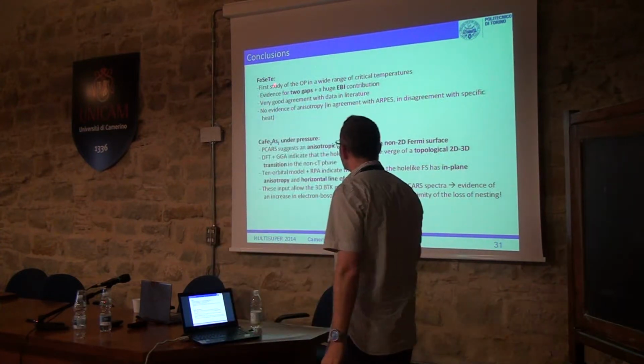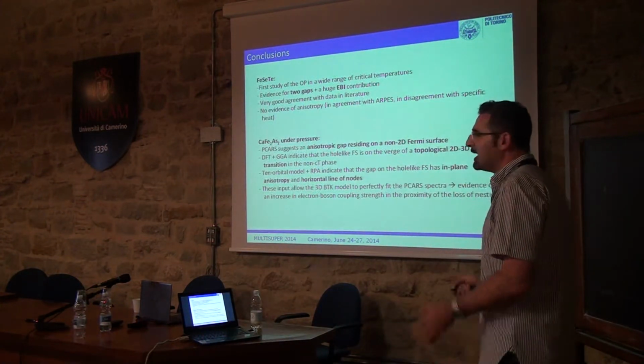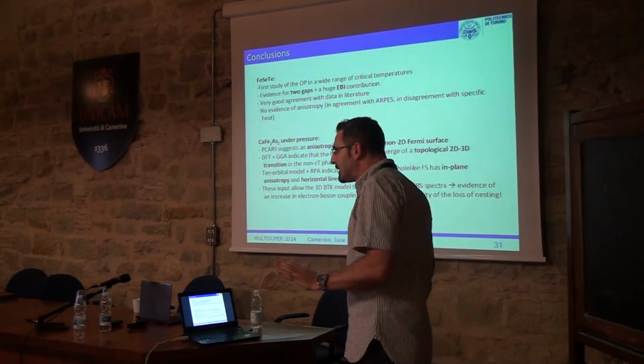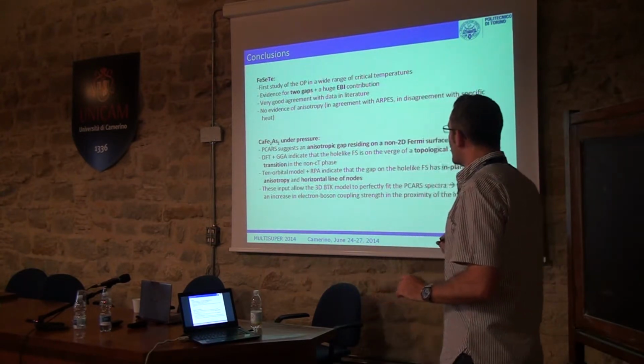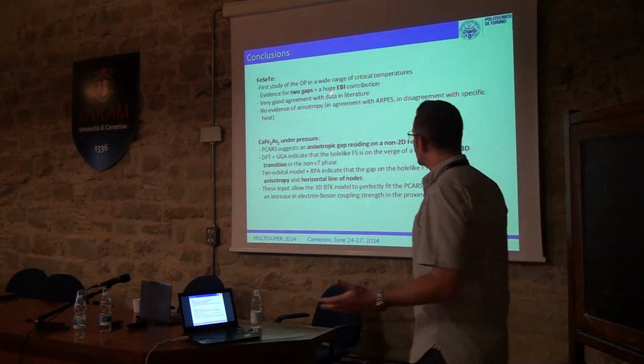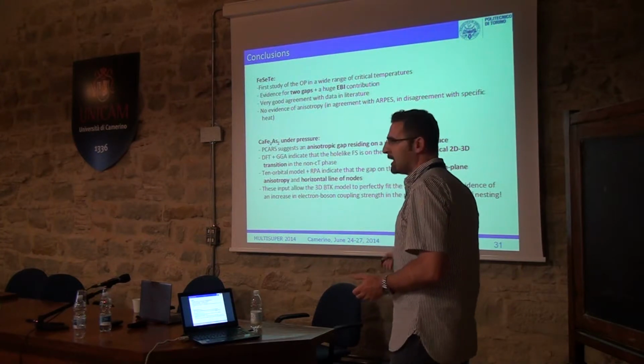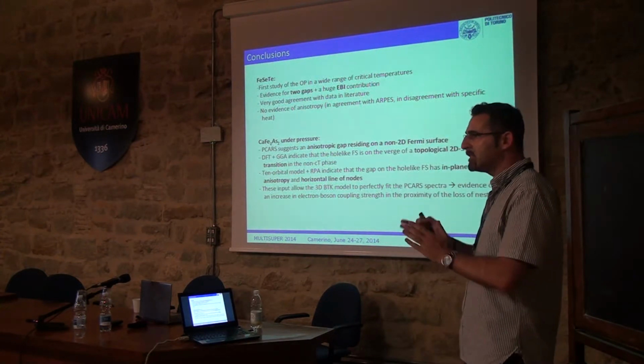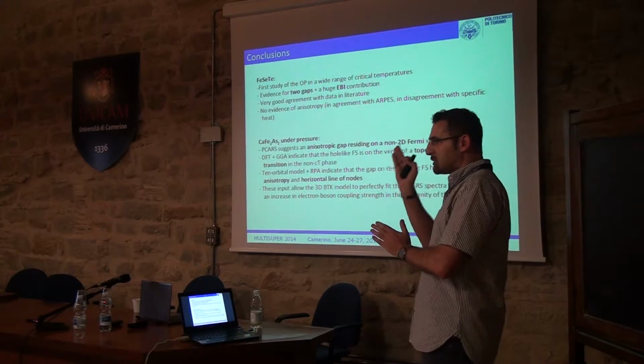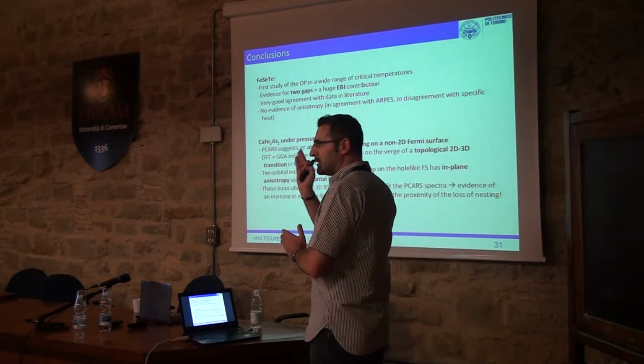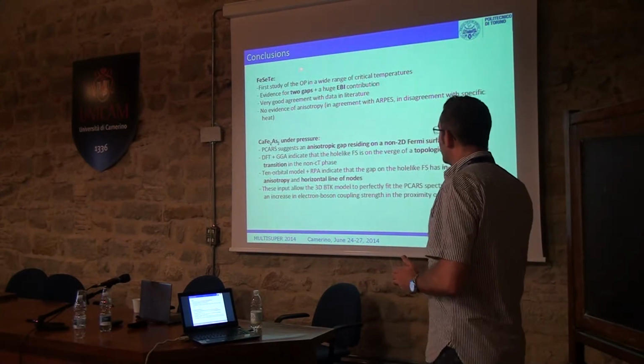So, in conclusion, in iron, selenium, tellurium, you find evidence for two gaps without any clear evidence of anisotropy, plus a huge electron-boson interaction contribution. This electron-boson interaction really has an energy that corresponds to the energy expected for spin fluctuations at this T.